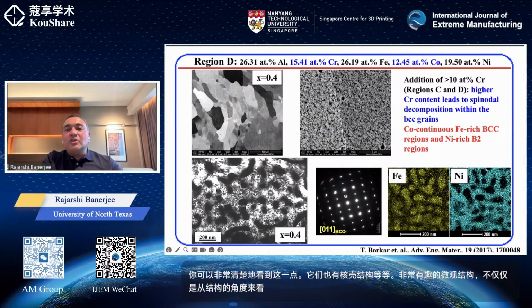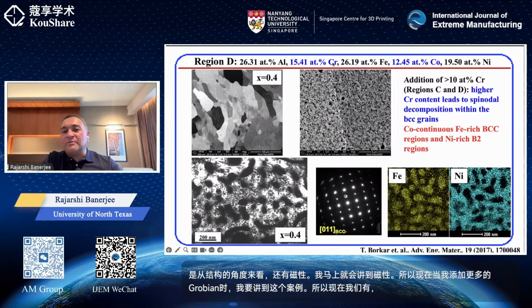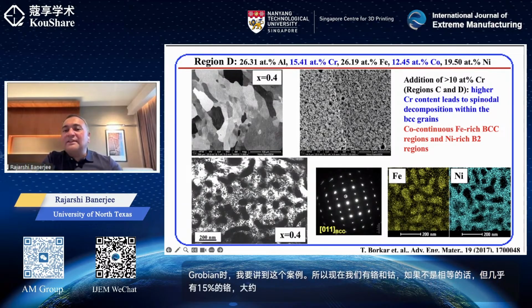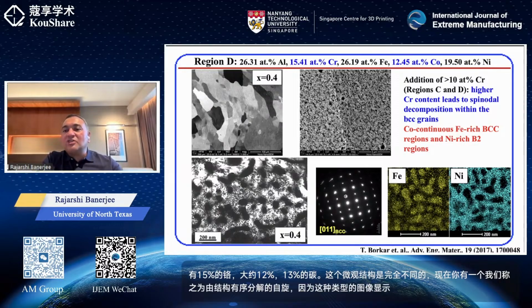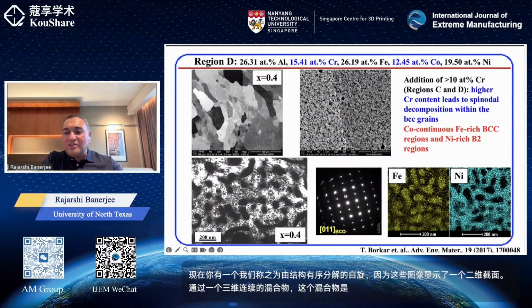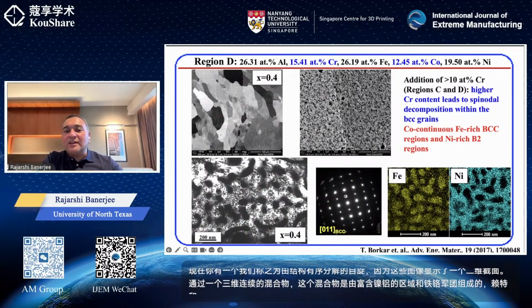So now I'm going to the case when I add more chromium. So now we have, if not equal chromium and cobalt, almost there: 15% chromium, about 12-13% cobalt. This microstructure is completely different now. You have what we would call a spinodally decomposed microstructure, because these images show you a two-dimensional section through a three-dimensional co-continuous mixture of nickel aluminum cobalt rich regions and iron chromium rich regions. This is a classic spinodally decomposed microstructure.